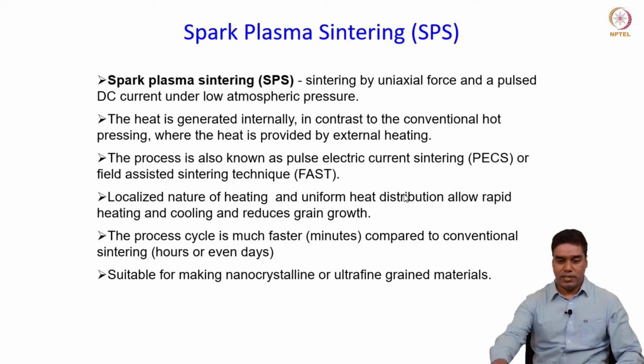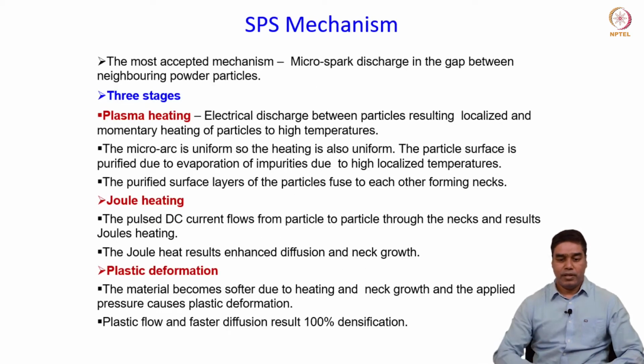So what we discussed in the previous class is that there are basically three stages in the spark plasma sintering process. First, there is an electrical discharge between the particles when the electric field is applied, and this leads to an intense localized heating which leads to purification and cleaning of the particle surface for better bonding between the particles. Okay, this also leads to melting at the contact points because of the high localized temperatures, and that again is helpful in bonding the particles together for the densification to occur.